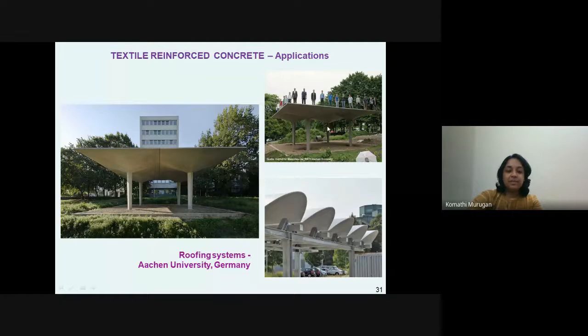We can see quickly one by one. The first here shows a roofing system which is present at Aachen University, Germany, RWTH, and we can see this system is around 35 to 40 mm thick, and we can see a lot of people standing at the edge of this roof, and the roof still was found to sustain. And this was a pilot project which was developed, and it is still under use or still under observation in RWTH, and it was found to work well.